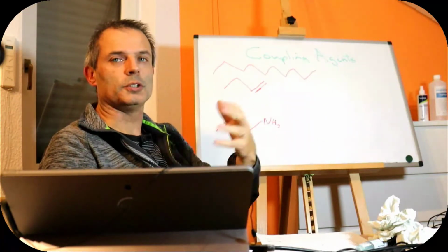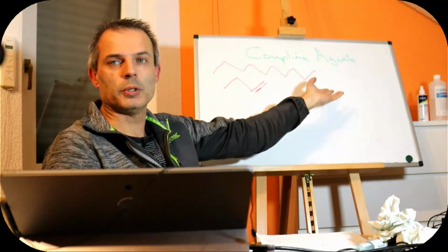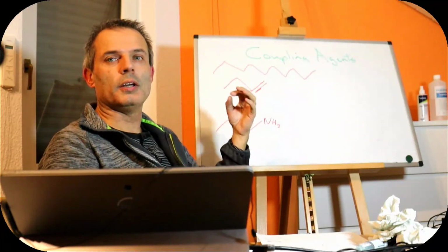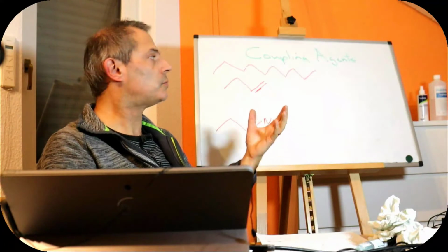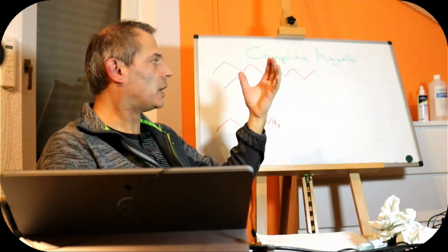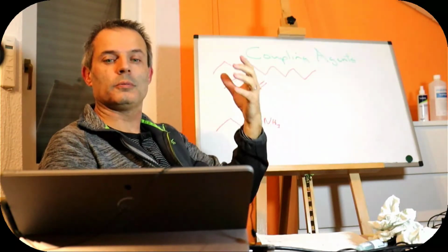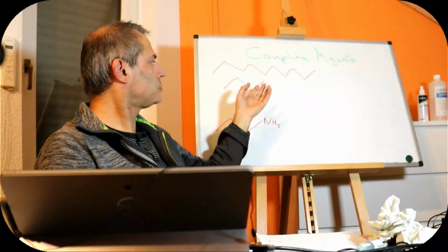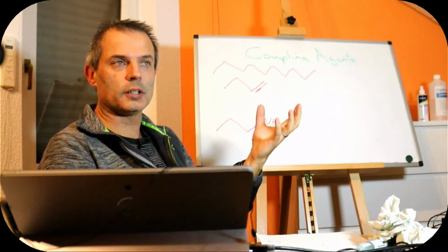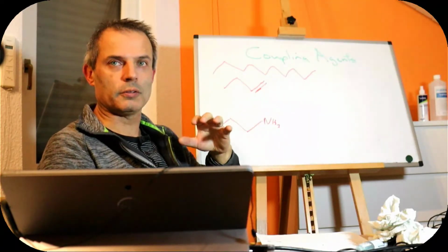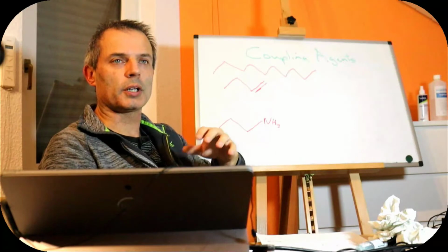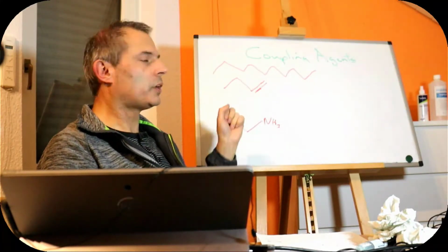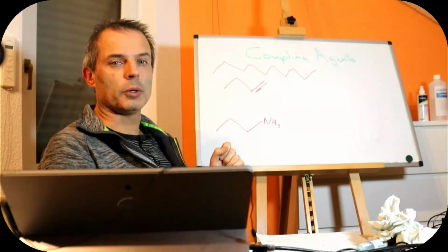If we're going to disperse it in polyethylene, this would obviously be a very good choice. We might also have a double bond if we want to do an attachment reaction. So if we're going to cover this with a reaction mixture that's going to form polymer by free radical initiation, this would be a fine way to start, because then it will be involved in the reaction and will actually link chemically all the way through to the surface. That isn't always a good idea, but if we want to do it, that could be how we would do it.